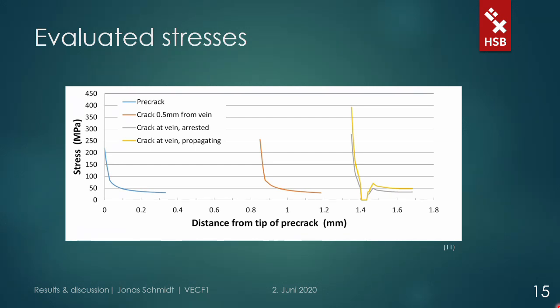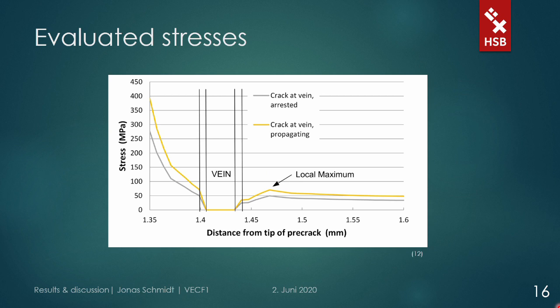Let's have a closer look at these two stress curves. Here the vein walls are indicated by the black lines. You can see that the stress is considerably lower within the vein wall, probably due to the thicker material compared to the membrane. What's interesting is that we see an increase of stress behind the vein, resulting in a local maximum. Keep that in mind as we will discuss it on the next slide, but first the actual application of the theory of critical distances.